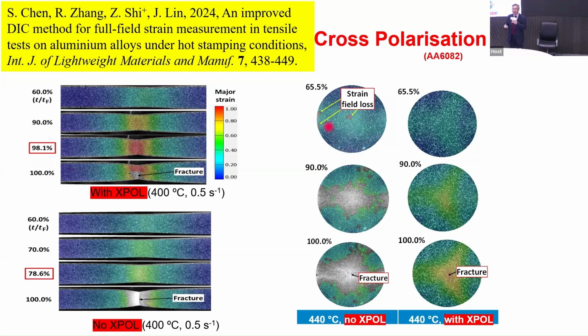For the biaxial testing, we look at areas with over 60% of deformation, where the peeling of the paint starts, and because the paint is very brittle, it's difficult for it to stay on. We tried various kinds of painting techniques, and eventually it's difficult to solve this. But at 90% of deformation, you can see a lot of paint has already disappeared. And with the cross polarization, you can see we can get the data almost close to failure. If anybody is interested in strain measurement using DIC, you can look at this paper to get the detailed technique.